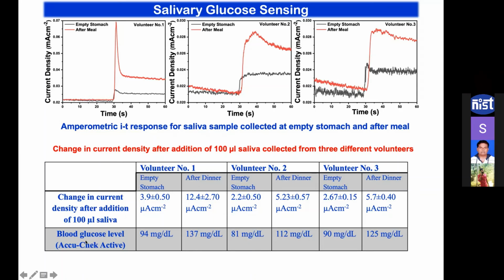Now the blood glucose level from the commercially available glucometer for empty stomach is 94 milligram per deciliter, and after dinner is 137 milligram per deciliter. So it increases after meals, and interestingly, it also increases in our sensor response from salivary glucose samples. So these results clearly show the correlation between the glucose levels in blood as well as in our saliva samples. But we need to get more results. We have to test the sensor response for more and more people.